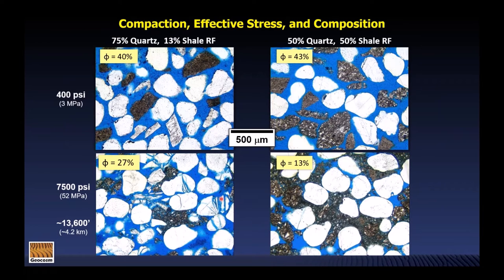Notice that although we actually have less bulk compaction over here on the left, we have more in the way of rigid fracturing of the quartz grains compared to over here on the right. So why is that? Well, even though we're imposing the same effective stress in this experiment, the shale rock fragments are deforming around these quartz grains, and that distributes the stress over a broader area of the grain. So even where we have quartz-on-quartz contacts, the stress concentration of those contacts is a lot less than over here on the left, where much of the stress through this grain pack is being distributed through very small areas of contact. And so the contact stress here was sufficiently high that we exceeded the yield strength of the quartz and we broke that quartz.